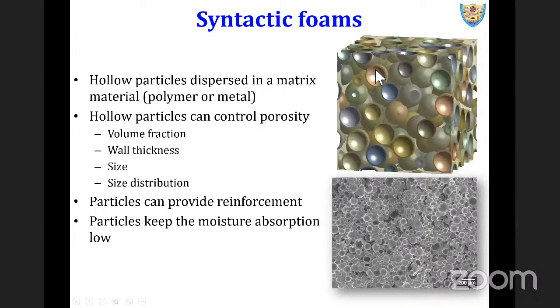So for the same volume fraction, the wall thickness might be 1 micron, 5 micron, or 10 micron. Likewise, the wall thickness will increase here. So with increase in wall thickness, for a given volume fraction, what is that moduli property? So this is the z-axis, which gives an additional flexibility to tailoring these properties of syntactic foams for any given application. And thereby these syntactic foams are being widely used in aerospace, automobile, marine, biomedical applications, wherein you have to tune the moduli of an implant to the bone and so on and so forth.